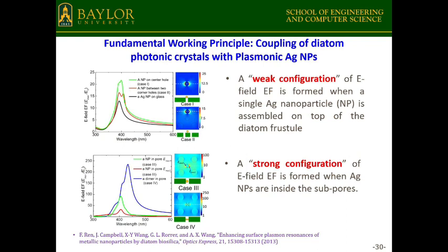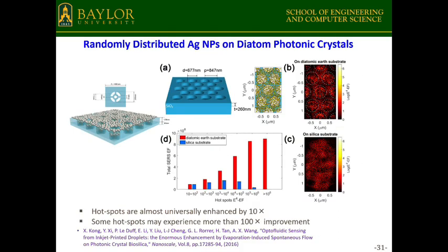So we integrate plasmonic nanoparticles on diatom, which is a photonic crystal material. When you put a metallic nanoparticle on the photonic crystal, the photonic resonance and the plasmonic resonance will couple together and induce even stronger optical field enhancement. For example, we show that if we put the nanoparticle on the surface of the diatom or inside the pores of the diatom, we can get significantly enhanced electrical field, and that can induce very strong SERS intensity. And this is a simulation to show you the nanoparticle may be greatly enhanced, but due to the time limit, I will skip the details.